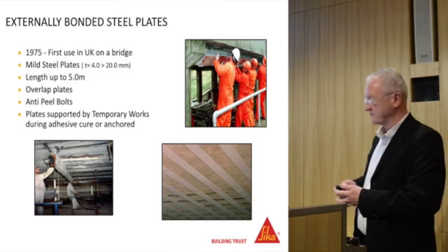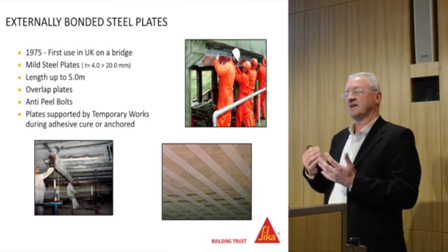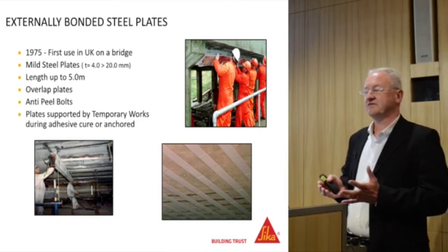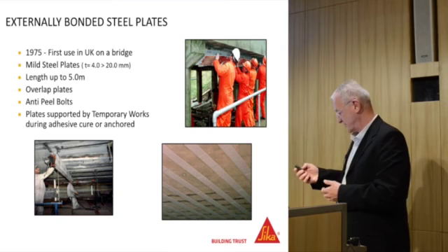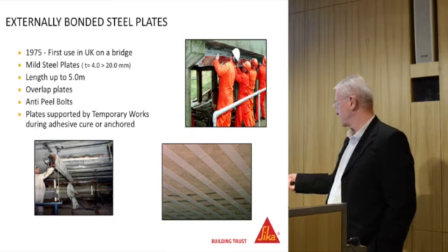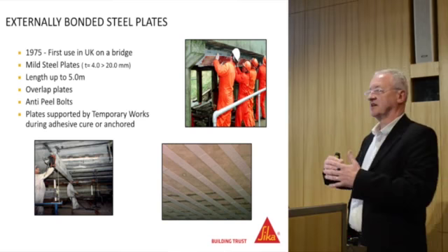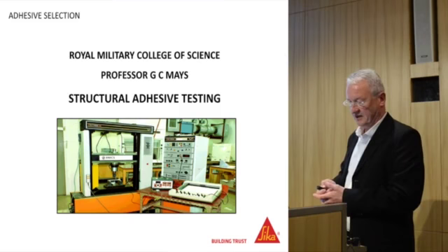Because the plates are so heavy and the adhesive isn't strong enough to stop them falling off during curing, you have to place some temporary support, which can be not only expensive but also cause quite a few access problems when trying to strengthen the structure. You can see here there's a pulley and beam system being used to apply pressure to the underside of the steel plates to hold them in place for about 24 hours before moving them on to another stage of the bonding.